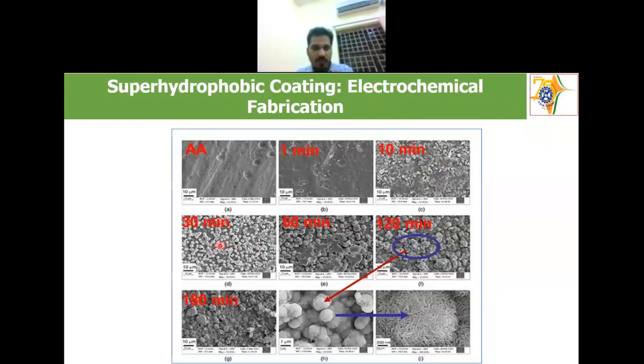You can see from 30 minutes onwards some kind of structure, with particles growing on the surface, but still it is not covered. And at 60 minutes also it is not covered. At 120 minutes it is completely covered and secondary growth also started.